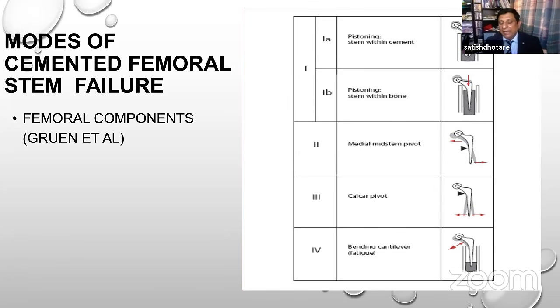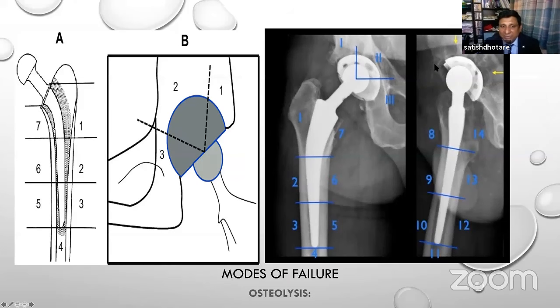Now, as I said in the beginning, the subsidence should be 1 or 2 millimeter within the initial 2 to 3 years. If subsidence is more than 5 millimeter, that means there is some problem. There might be some breakage of the cement mantle. There might be less cement mantle in one area around the tip of the stem, which might be touching the cortex or breaking the remaining thin cement mantle. And that could lead to loosening of the stem or loosening of the prosthesis. So in the first one, the pistoning type, the stem is within the cement, so there is subsidence which is high.